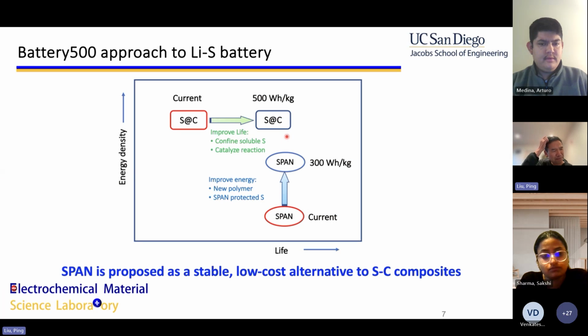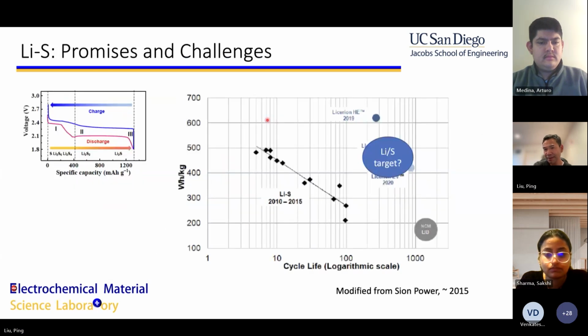So what we do in the consortium is that traditionally most of the lithium sulfur battery work has focused on making nanostructured sulfur in carbon as a cathode material. Again, like I said, making it nano itself does not make it active. Putting the sulfur into a nanoporous carbon gives the sulfur more surface area to react with, to pick up an electron and combine with lithium. Unfortunately, as in that inverse log plot, which is just another way of saying it's an exponential decay, we try very hard to improve this plot. Is it possible we can move away from this line and to a happier place?